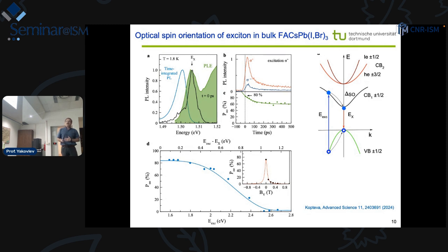Another surprise in this experiment was, okay, the first surprise that we can reach a very high optical orientation degree, but one can predict this from the simple band structure, that we have only spins 1/2. But another surprise comes when we start to move our laser from the nearly resonant excitation of the exciton to higher and higher energy. And here you see this optical orientation degree of 80%. It stays constant without decaying nearly up to 1/2 electron volt. For common semiconductors, it's very unusual, because in common semiconductors there is a spin splitting, the Dyakonov-Perel mechanism, for the higher-lying states, and the spin relaxation there is much more efficient than at the bottom. So the relaxation by acoustic and optical phonons will nearly destroy your optical spin polarization. Here, we have no destruction at all. So it starts to decay only after 1/2 electron volt and disappears at 1 electron volt.